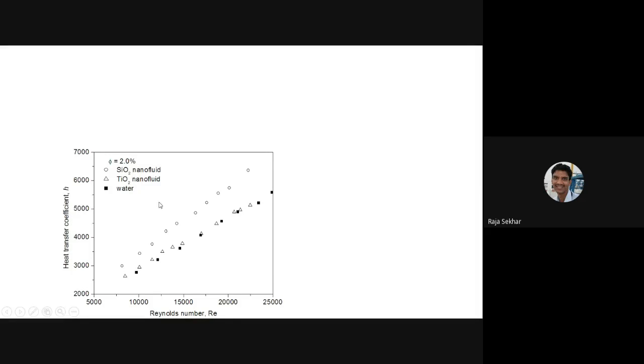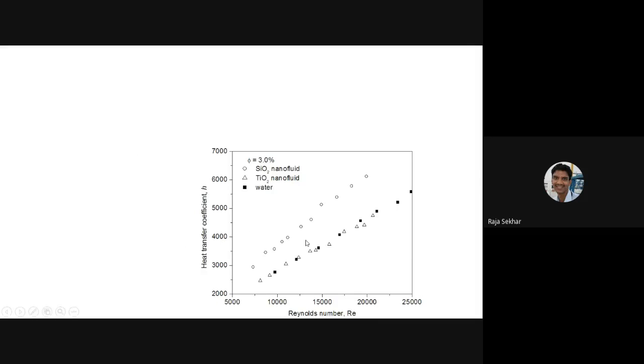That means more than 2, TiO2 should not be preferred. But SiO2 is giving you a better enhancement rate compared to TiO2 at 2%. So you should limit the volume concentration that you add to the base fluid before going to the actual application. Similarly, we tested for 3 also, and it is showing the same thing. TiO2 is having the same heat transfer rates as compared to water, but SiO2 at 3 is still giving better enhancements. So if you want to prefer SiO2 and TiO2 for different concentrations, you can use this data for the respective application.